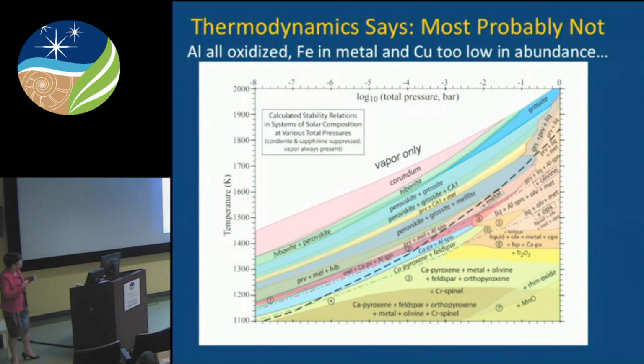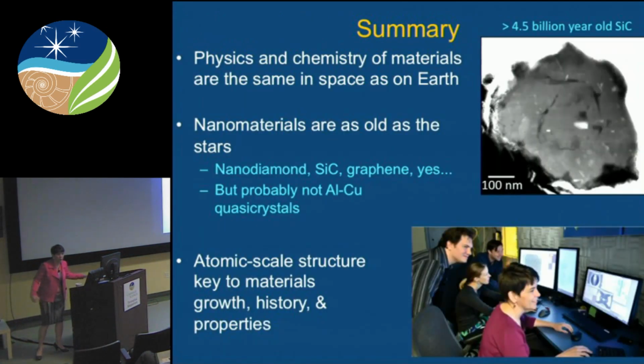The way to distinguish is to go in there and look for signatures of a cosmochemical origin of that aluminum copper-rich phase. I'd have to say that there are data that indicate those signatures are not there. They have not yet published, say, magnesium-26 measurements, as we saw in the supernova-originated silicon carbides and so on. So it breaks my heart a little bit to say it, but this quasi-crystal is not from space. It's most likely synthesized in the laboratory, and the two phases met each other somewhere in a diamond anvil cell in a terrestrial laboratory.